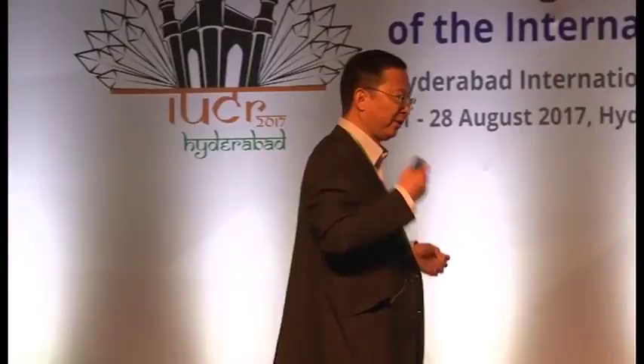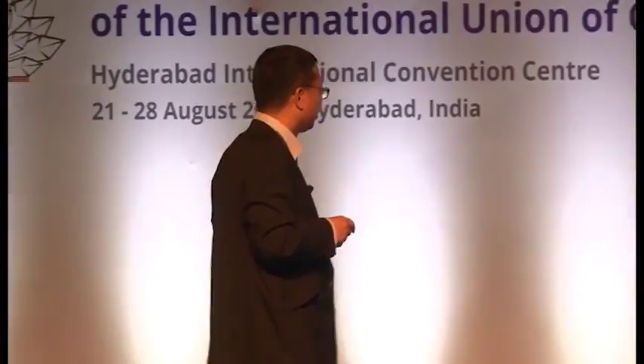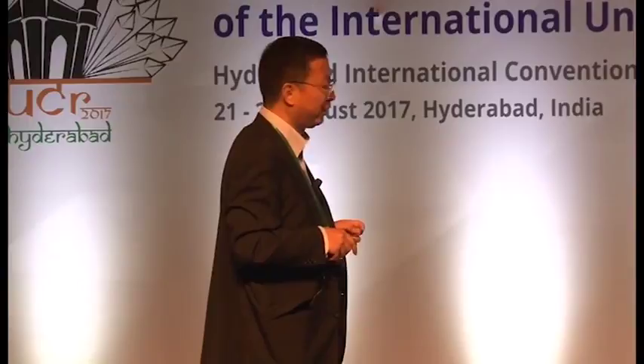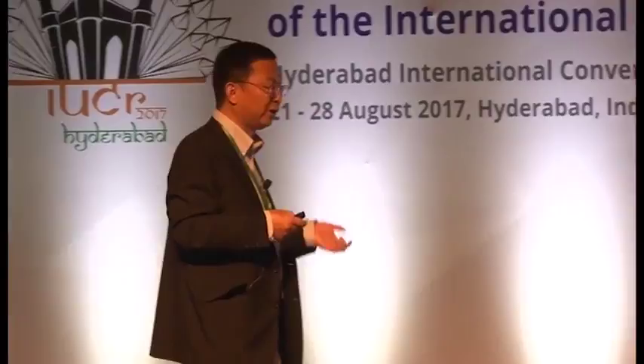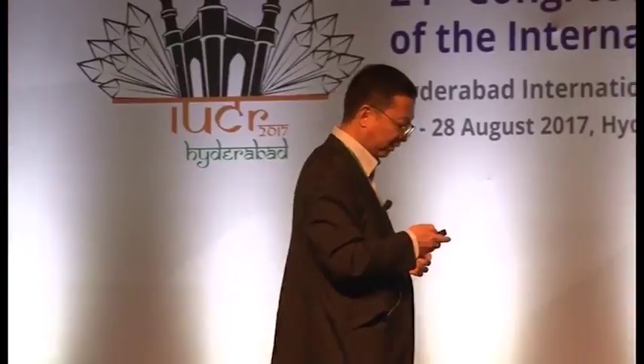How about the easy axis for the molecules? Luckily, we got a quite big single crystal of the compound. Three beta-diketone ligands are connected to dysprosium, and the two water molecules were replaced by pyridine, so we got quite big single crystals. The crystals crystallized in triclinic space groups. In this case, we had the opportunity to use angular dependent single crystal measurements to determine the easy axis for the compound.